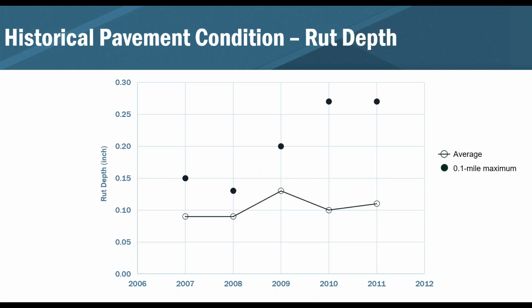So on the rut depth, again the same thing. Typically, patching and fatigue cracking, you don't solve a rutting problem. And so that's what you can see here, that the rutting, at least on the maximum values, is still increasing, which again, I think the issue was more fatigue related than rutting. And even at that, the rutting is pretty low. Even in the worst case scenario, it looks like it's only a little bit more than a fourth of an inch. So it's not anything I think that the DOT was seriously concerned about at this stage.